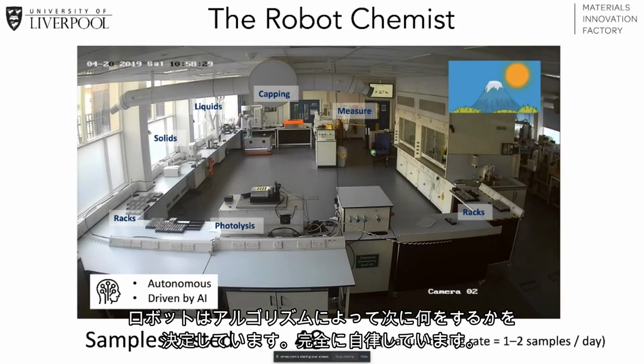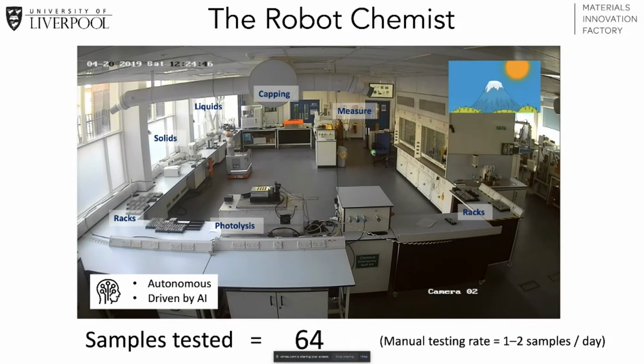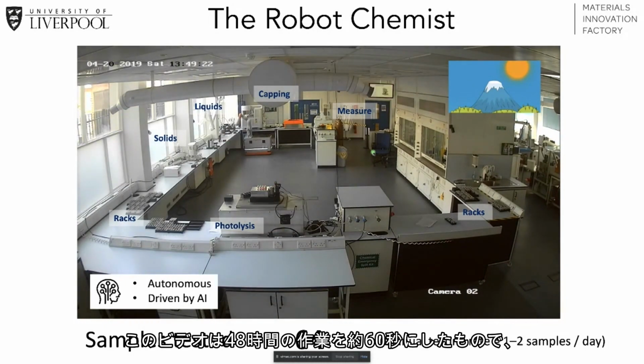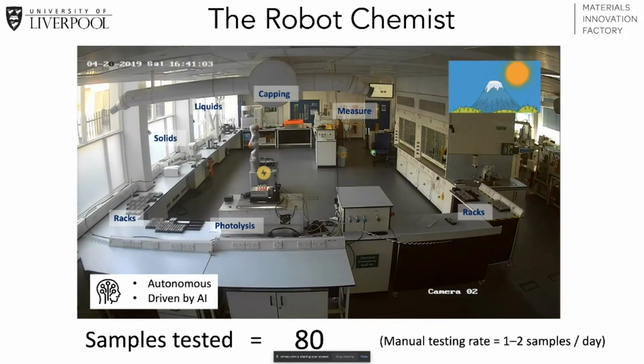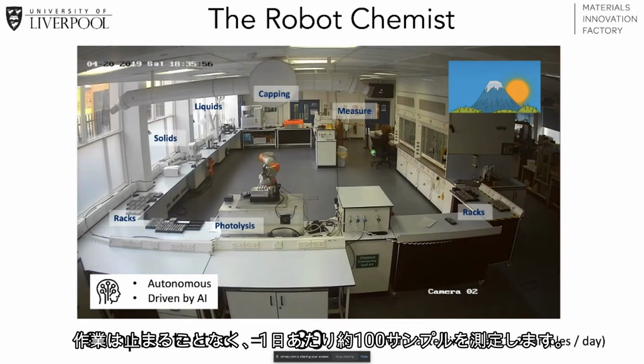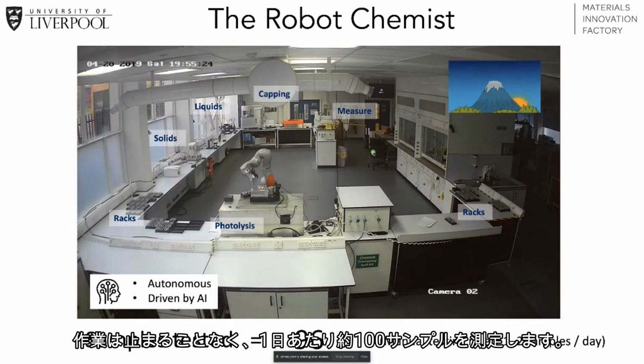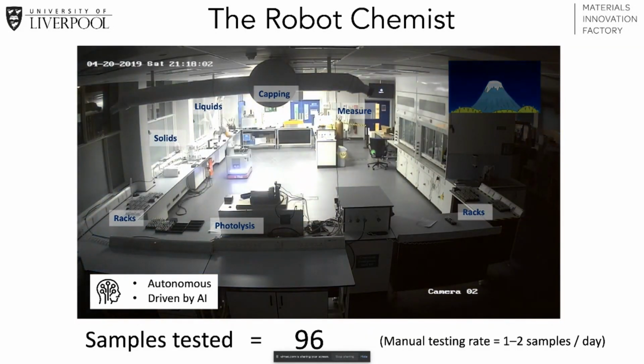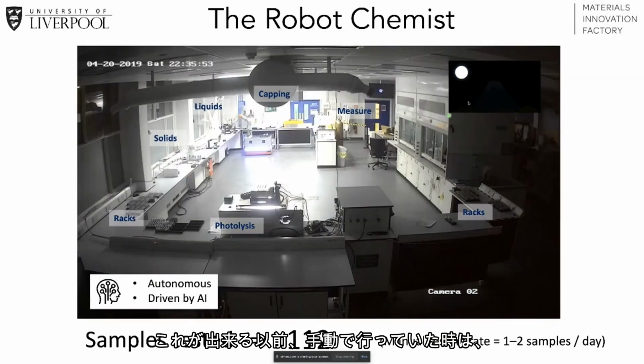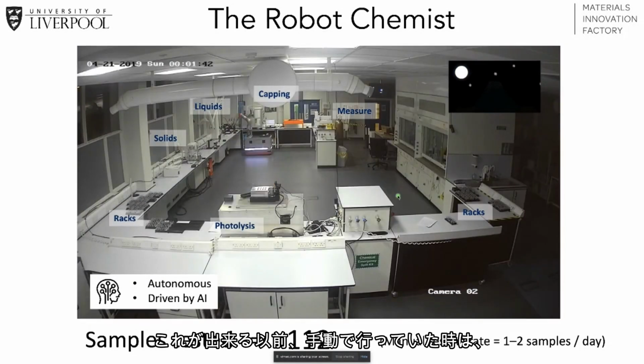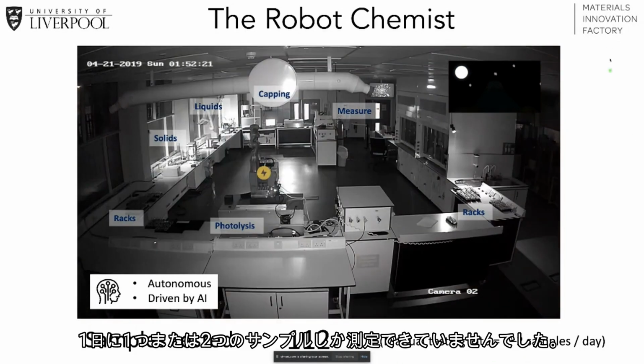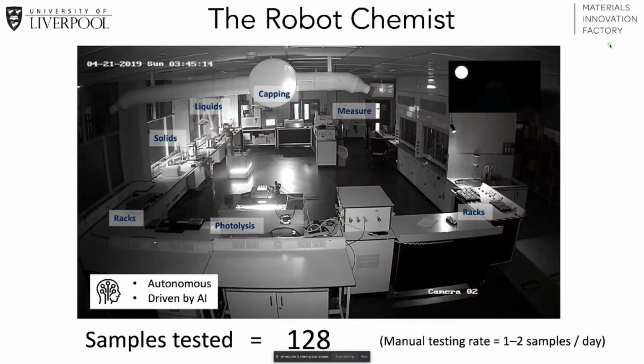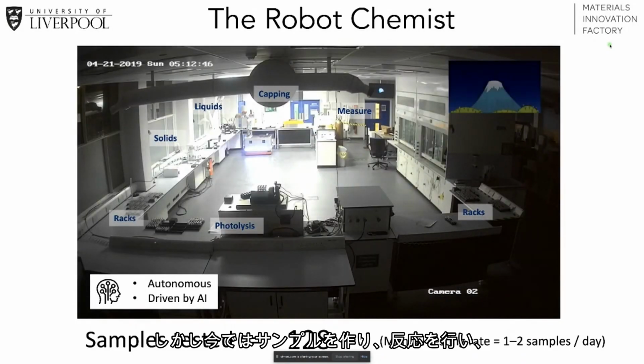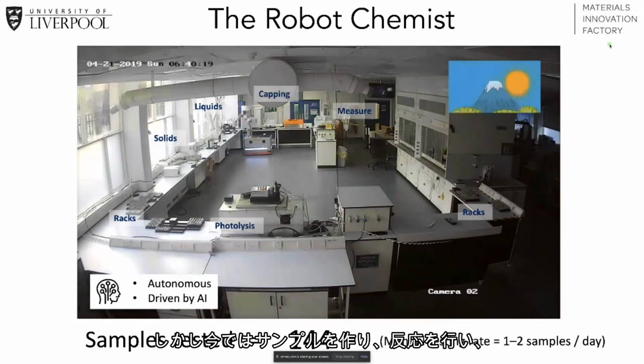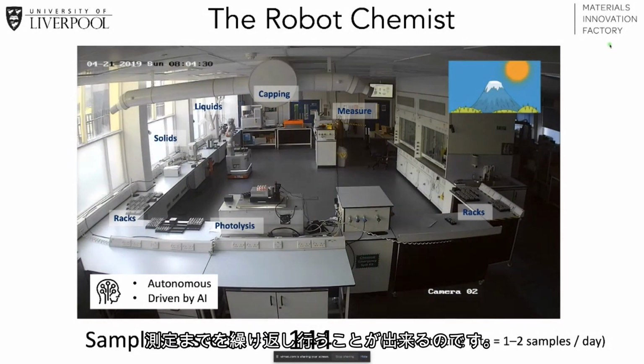So it's fully autonomous. And in this video, which runs for about 60 seconds, it works for 48 hours without stopping. And it measures about 100 samples a day. And for comparison, before we built this, when we were doing it manually, we could measure 1 or 2 samples a day. But I should say it makes the samples and does the reaction and does the measurement in a loop.